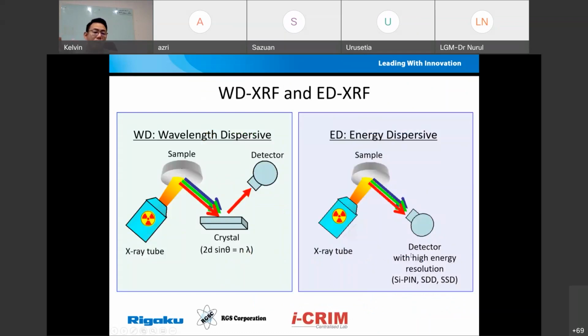So what people always talk about, EDXRF and WDXRF, what is the difference? It's actually very simple. In the WDXRF, you have a crystal, a detector, the sample and the X-ray tube. How do we separate all the signals? When the X-ray hits the sample, all the signals come out simultaneously. So the crystal does the work of choosing which signal can be seen by the detector, by satisfying Bragg's law. This is the same law we use in XRD, except in XRD we are measuring the d-spacing, and in XRF we are measuring the lambda.